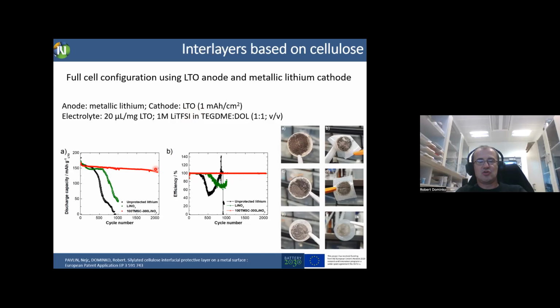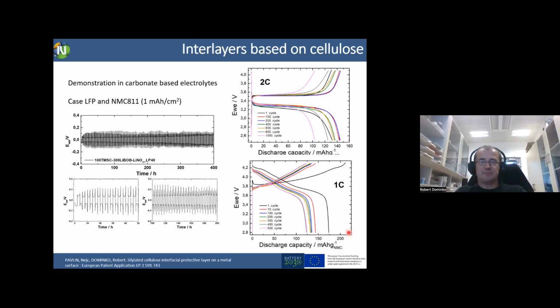we just wanted to show that this can be cycled for a long time, and compare with unprotected lithium and also an electrolyte that contains lithium nitrate. So this worked very well in 2000 cycles, and you can see there's still almost no sign of any penetration of dendrites into the separator. And that methodology, that protection layer, also works very well with LFP chemistry, 2C cycling. 1000 cycles was achieved,